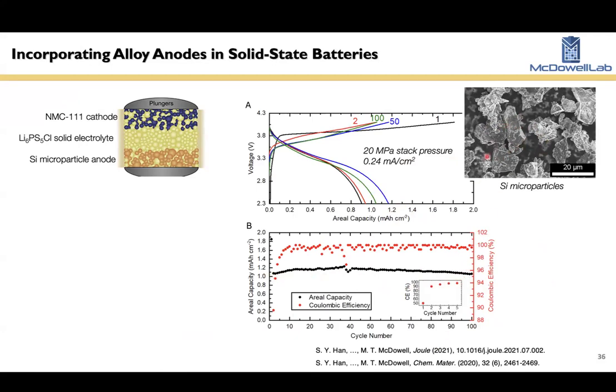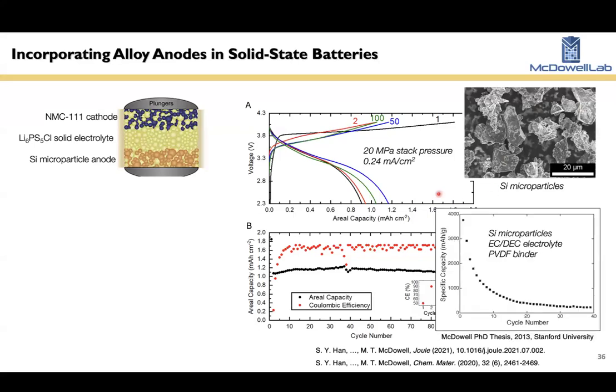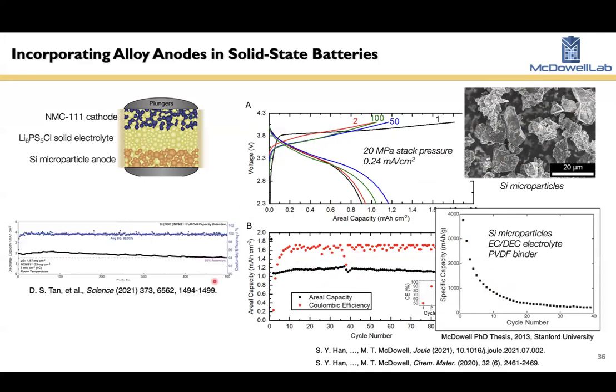This was really quite surprising when we initially started this work 4 years ago, because if you do the same thing with these sorts of microparticles in liquid cells, you see really rapid capacity decay in a half cell. Really terrible performance. This is because these particles break up into pieces and there's a lot of SEI that forms. So intrinsically, you can have the case where a solid-solid interface is chemically more stable than a solid-liquid interface when you're using these alloy materials. And this leads to improved cyclability.